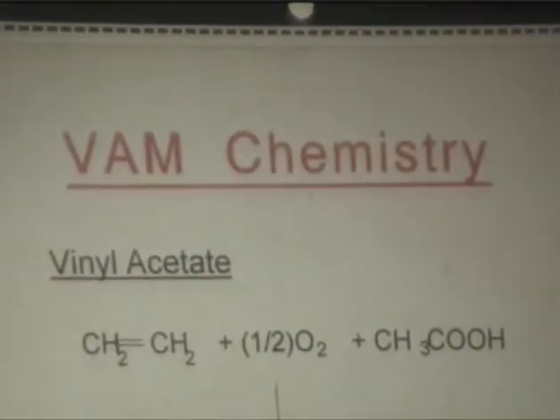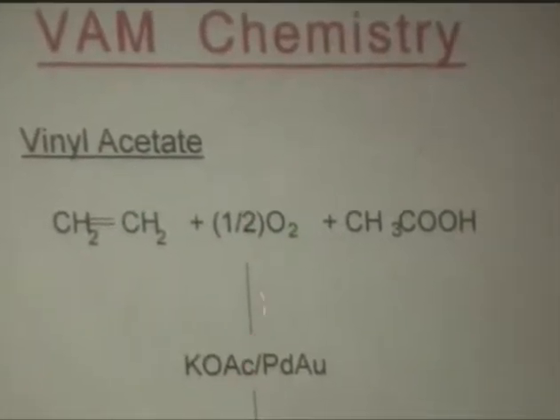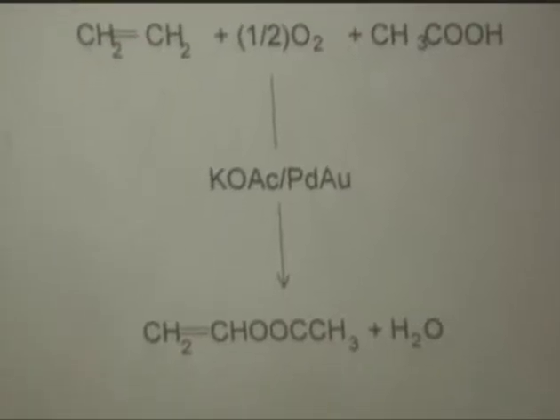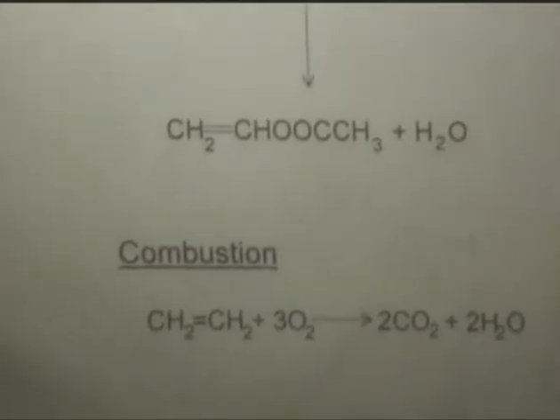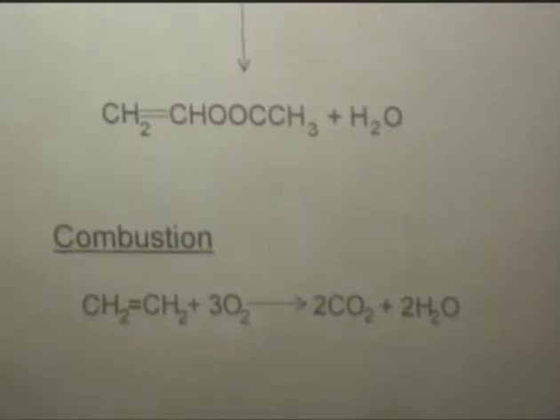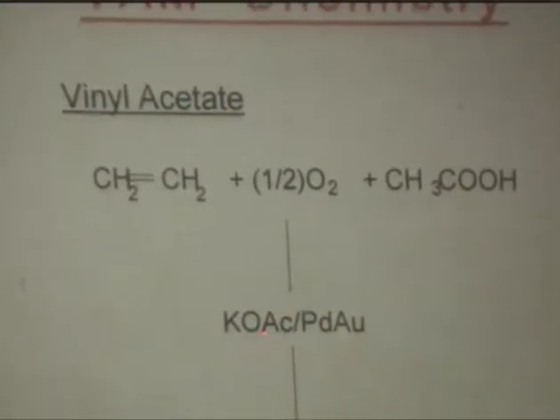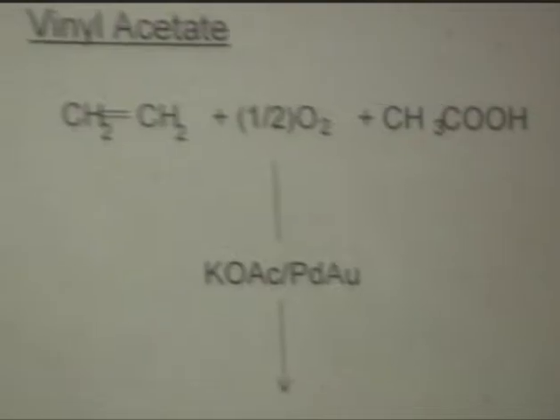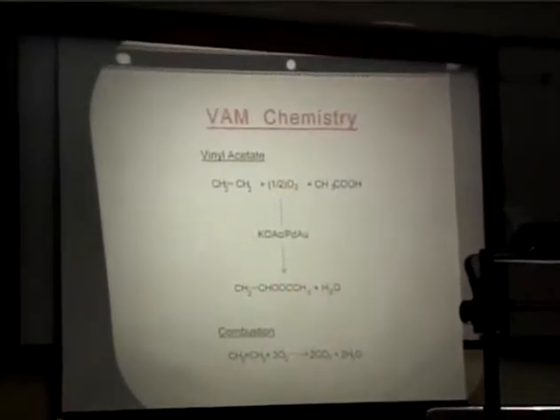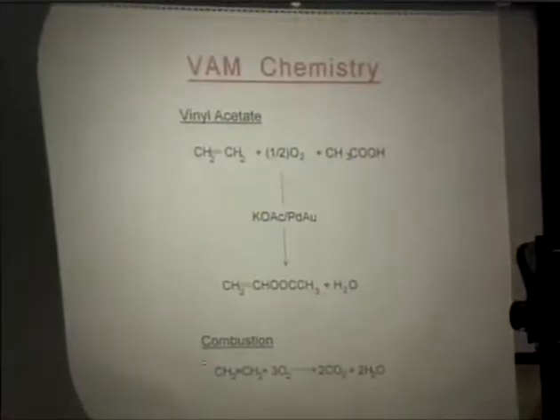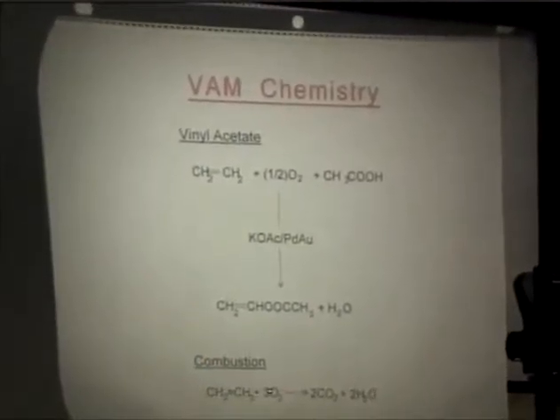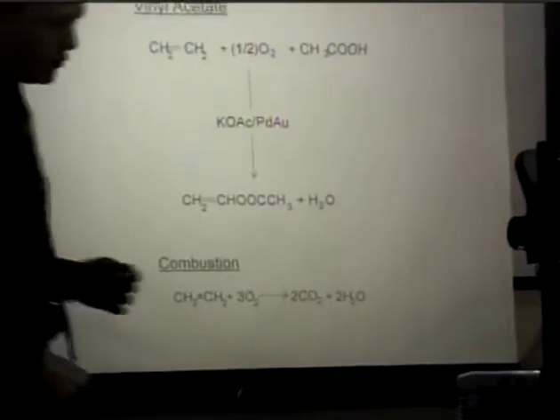To give you a feel for what vinyl acetate is, I'll begin with this simple reaction chemistry. It is an unsaturated molecule made by the combination of ethylene and acetic acid in the presence of oxygen. We use a supported palladium gold catalyst, which we promote with potassium. It makes vinyl acetate, and the driving force there is the production of water. The competing reaction which we want to avoid is combustion of the ethylene to make CO2 and water.